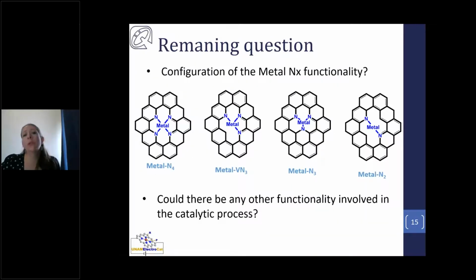Yet, even though we do see this, we still have a lot of questions remaining on how the actual active sites look in this type of material. For one, even though the metal is probably the predominant active species, we don't know what it looks like. It could be coordinated to 4 nitrogens, as we usually draw it, but it could also be coordinated to a different number of nitrogens, and there could be vacancies that are key for the catalytic process. In addition, it's not only the metal that is involved in the catalytic process. In this type of very heterogeneous material, more than one site can contribute to the reduction current.